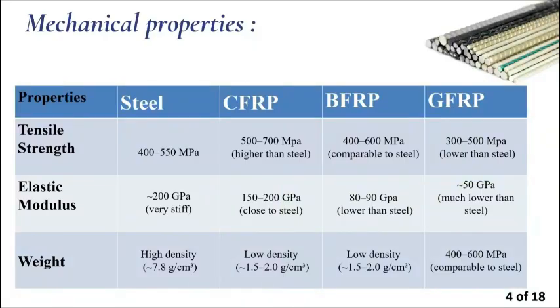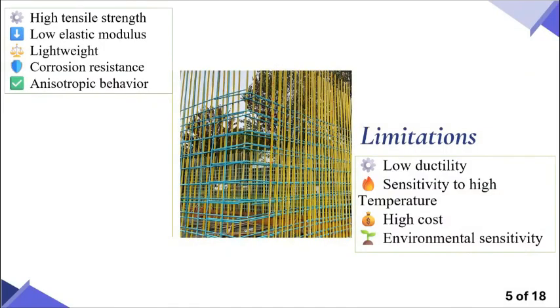Now let's move on to the mechanical properties, or what makes FRP special. Actually, it has high tensile strength, especially carbon FRP, compared to traditional steel. Secondly, it has a low elastic modulus. Yes, it is strong, but it is less stiff than steel. And finally, it is lightweight, which is one of the most significant advantages of FRP, as it has low density compared to steel. Without forgetting corrosion resistance: FRP does not corrode, which improves durability, especially in harsh environments. And it has anisotropic behavior, which means it has high strength in the direction of the fibers. This helps engineers place FRP exactly where it is needed.